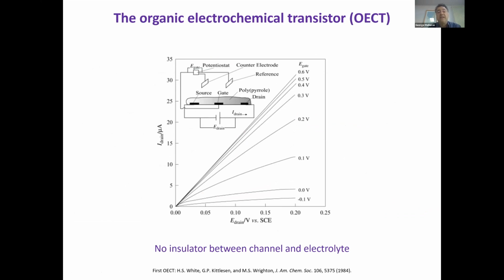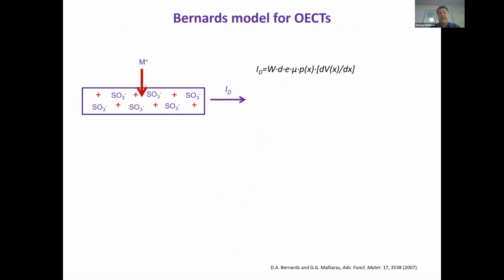The third type of evidence comes from devices that are called organic electrochemical transistors, which have been developed by folks at MIT, Mark Wrighton's group at the time back in the 80s. And they were regarded as an electrochemical curiosity. Here you have a polymer between source and drain electrodes. You have a gate electrode in the electrolyte, and you can dope or de-dope the polymer and then measure its conductivity. So it was viewed as a way to study the doping of these films. Later on, electrical engineers got their hands on this and started looking at this as devices, semiconductor devices.